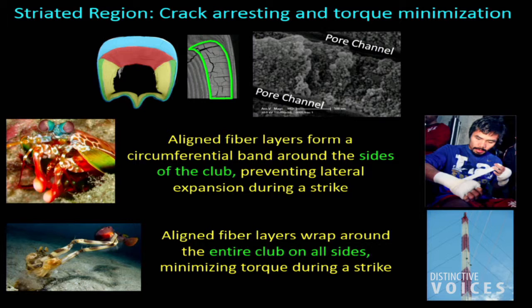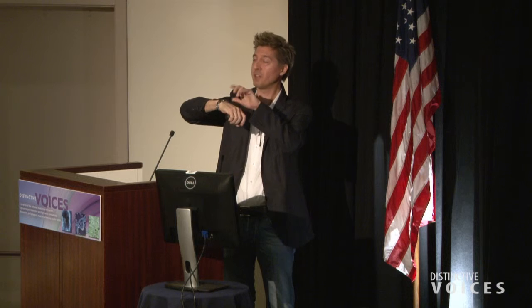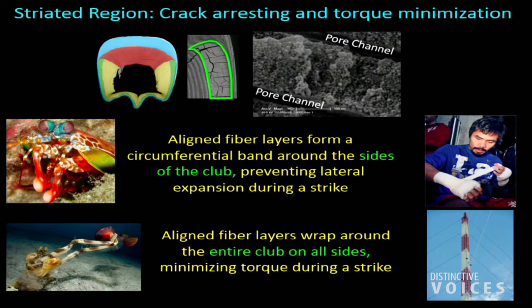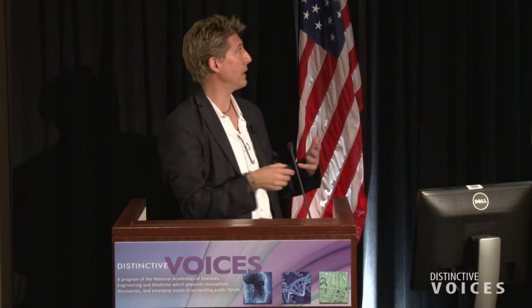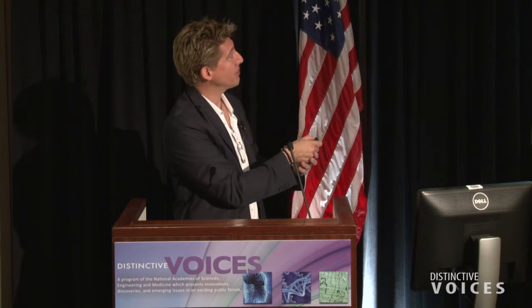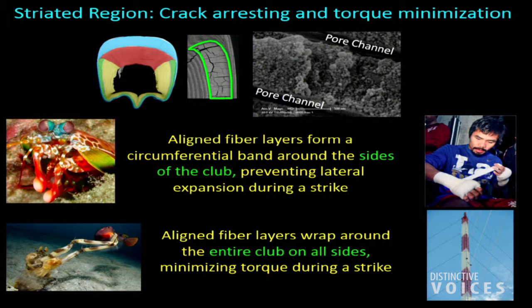Okay, this side region. This is what I call the striated region. It's located here in green. These are fibers that I show here. They're mineralized fibers that are literally, just like these beads that I'm wearing on my wrist, wrapping around the entire club circumferentially, and they keep the club under compression. So you see Manny Pacquiao wraps tape around his fist before a fight, and that's because when he punches, there's a tendency for the fist to expand laterally. Well, ceramic materials don't do well when they're pulled in tension. So by keeping things under compression, you reduce the likelihood of cracks propagating and failing. So this band of fibers that wraps around the club keeps everything compressed.